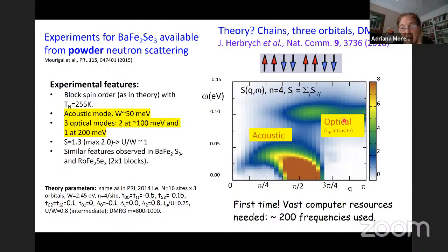On the other hand, the optical mode occurs at high values of momentum, and it seems—as I will show you later—that the value of omega at its position is correlated to the Hund coupling. We believe this mode arises from a spin flip within the same block.